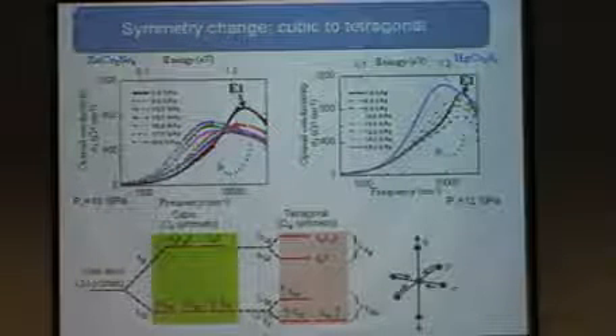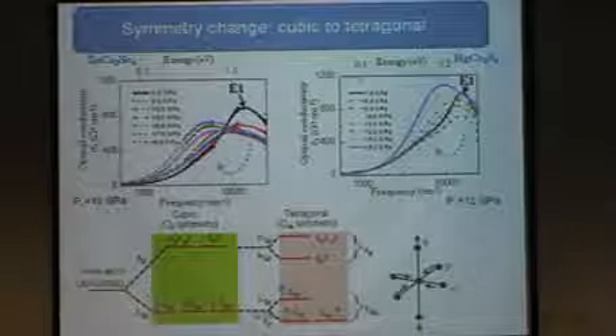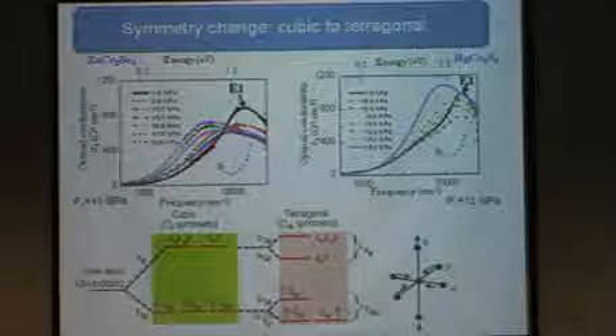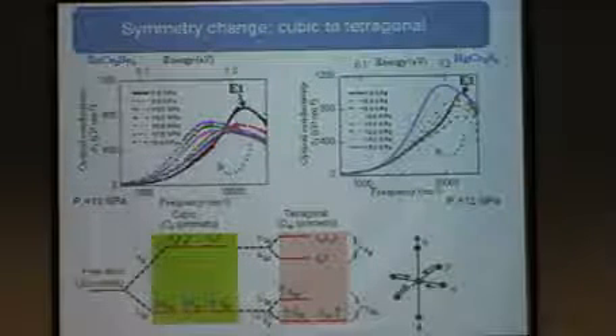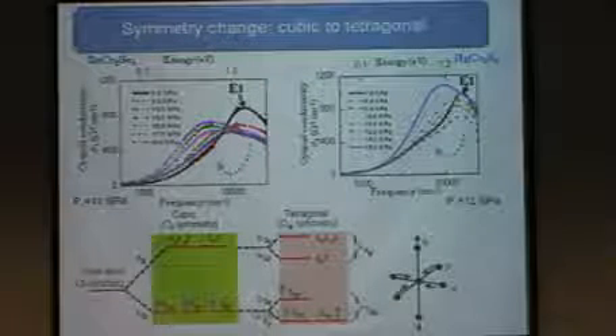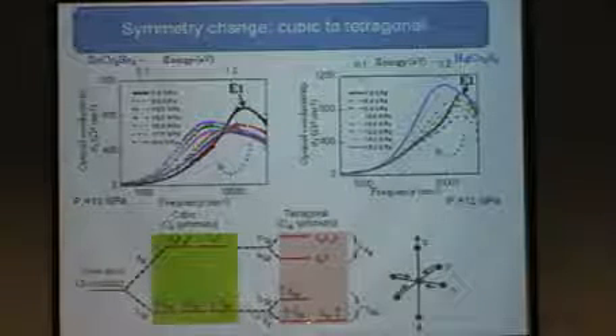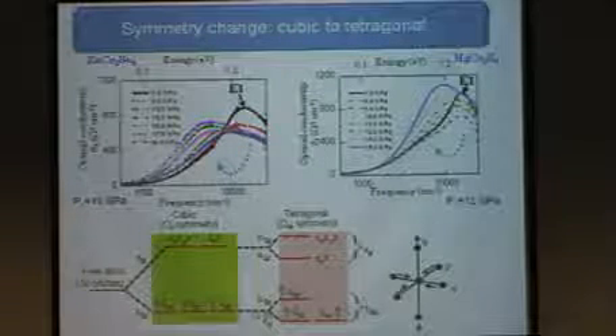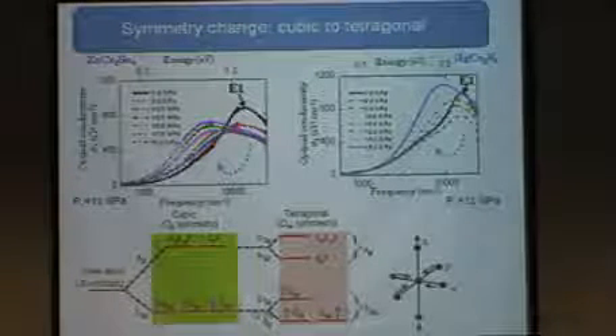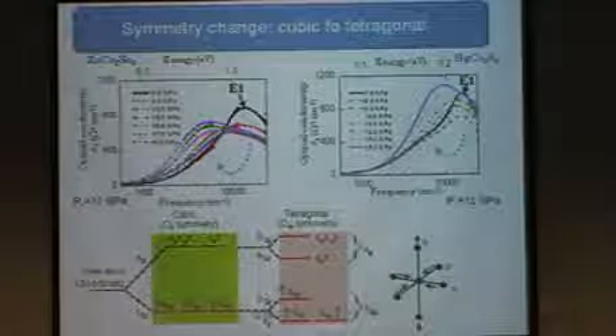Okay, we have talked about that when the lattice is compressed, it changes the symmetry from cubic to tetragonal. If we consider the tetragonal symmetry at the transition metal ions, then we can suppose that if there is elongation along the z-axis and contraction along the other two axes, then the degeneracy of these t2g orbitals is partially lifted, and the eg orbitals become non-degenerate.